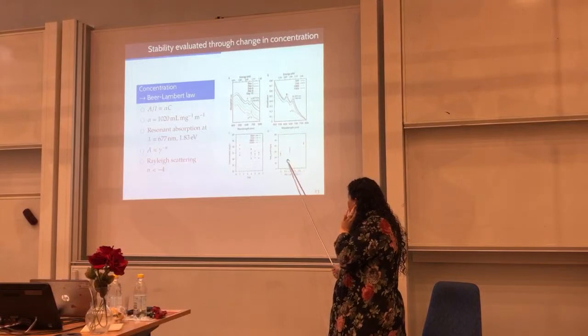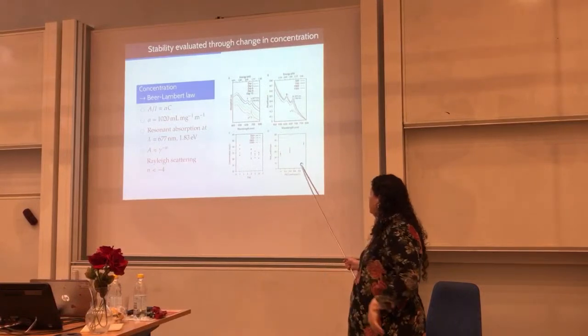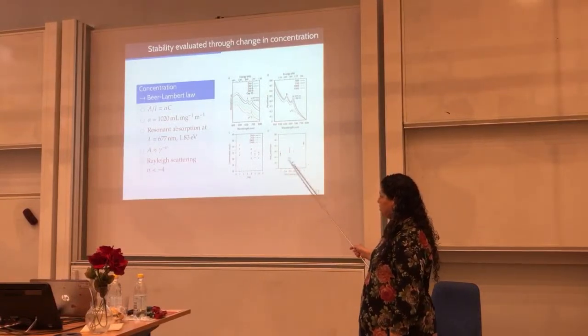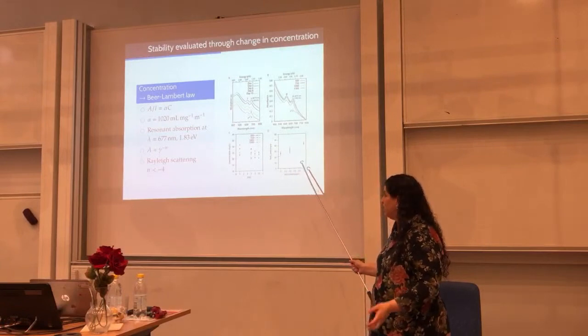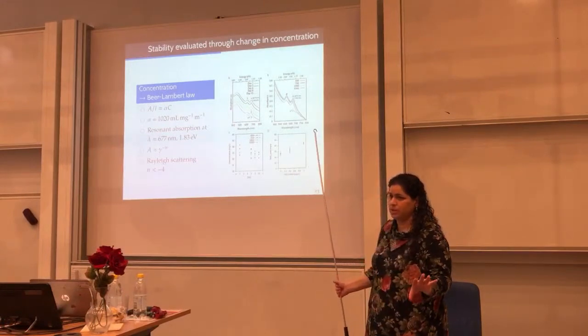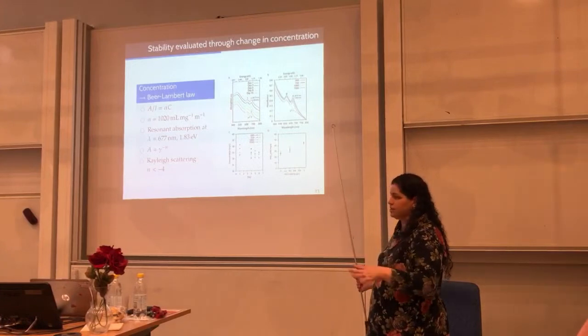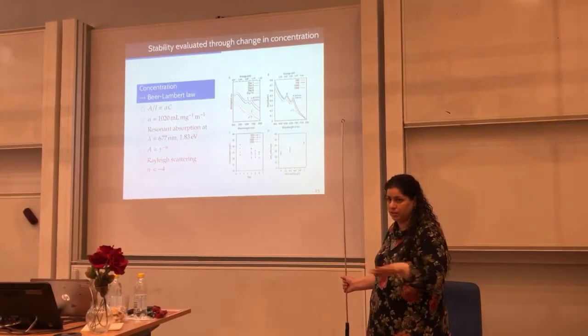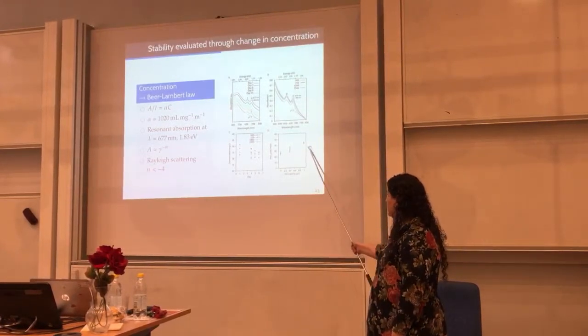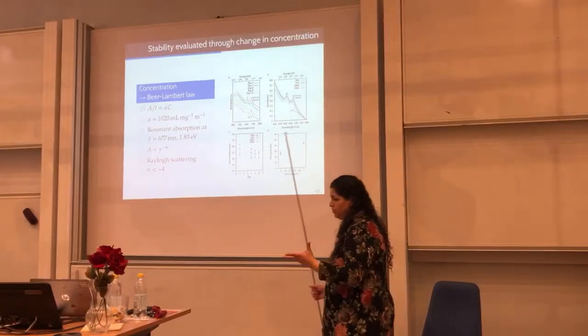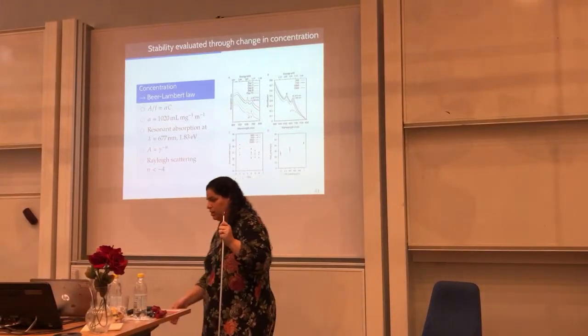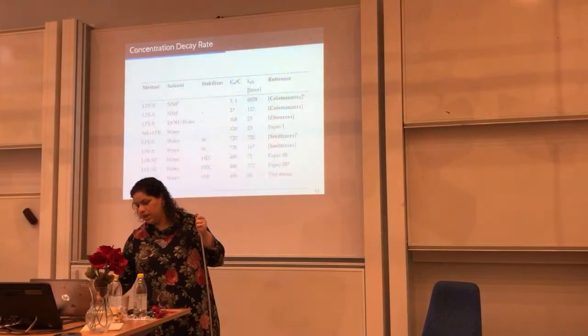When you use HEC, we could achieve different concentrations depending on the amount of HEC that you have. With surfactants, we didn't observe this. We observed that with surfactants there was a monotonic increase in the concentration. But with HEC, we achieve up to 40 milligrams per liter at 1 gram per liter HEC concentration.